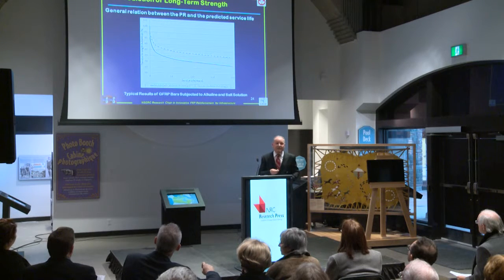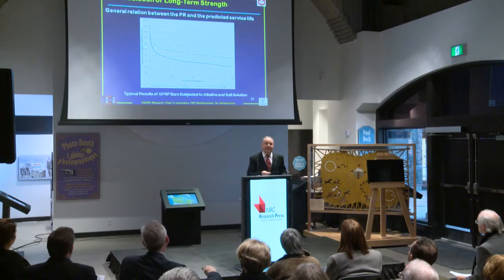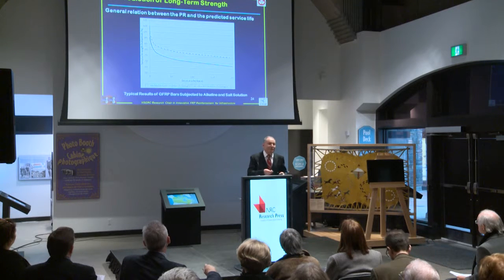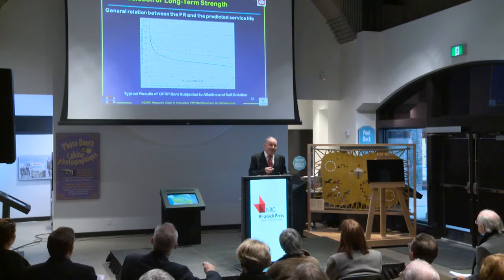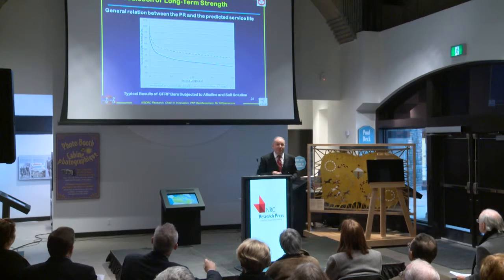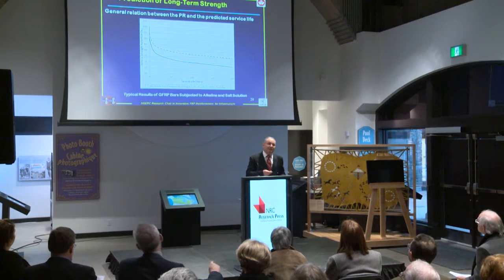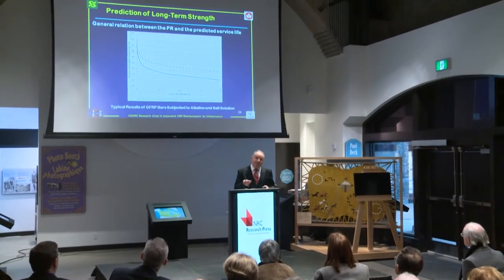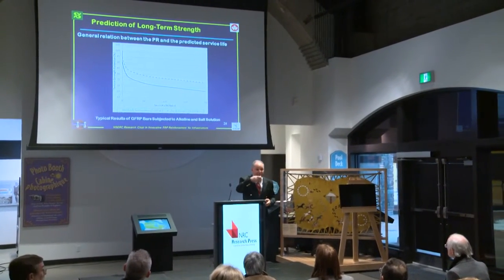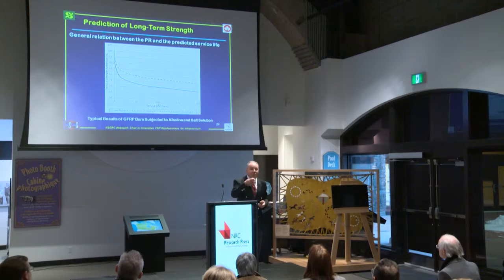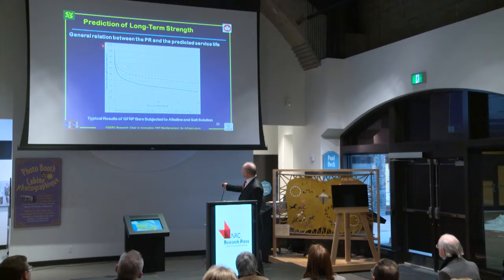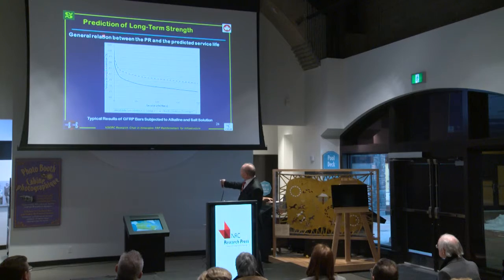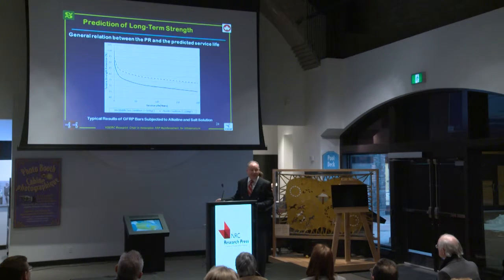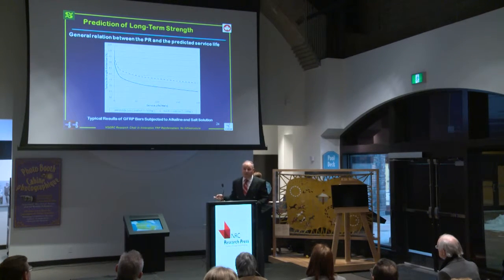Also, we engineers are asking about how this material will last 50 years, 20 years. So we tried accelerated aging tests in the lab using elevated temperature to determine, for example here, how the tensile strength of this material could vary depending on the years. Here I'm simulating the behavior of this material in terms of tensile strength, because tensile strength is one of the important strength criteria to be used in the design for bridges and so on when using this material.